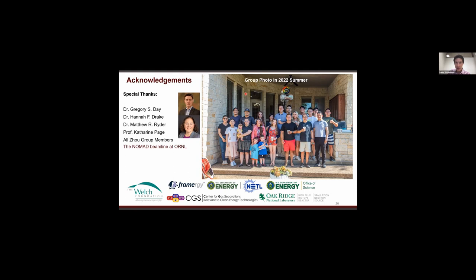Sihai Yang says, is it possible to gain structural information on the active sites for either adsorption or catalysis of these MOF-derived carbon materials from the neutron PDF analysis? So for this, when you have the MOF-derived carbon, and the active site is an open metal site or, for example, a pocket where you have nitrogen that can bind, I think the answer is that since it's an average structure, it's actually quite difficult to get very accurate information there.